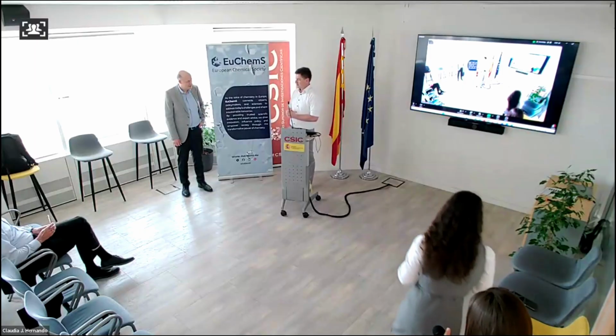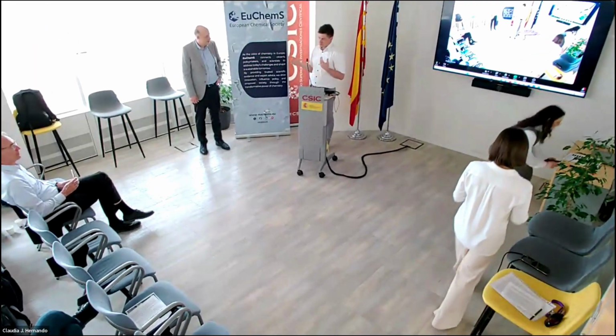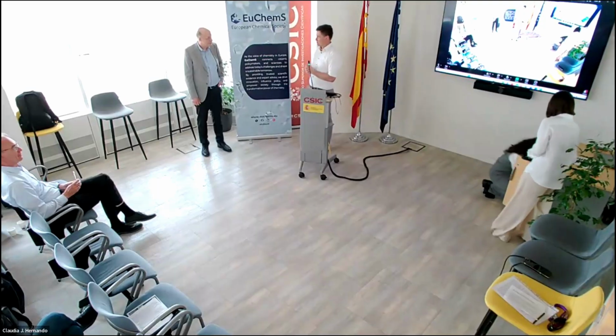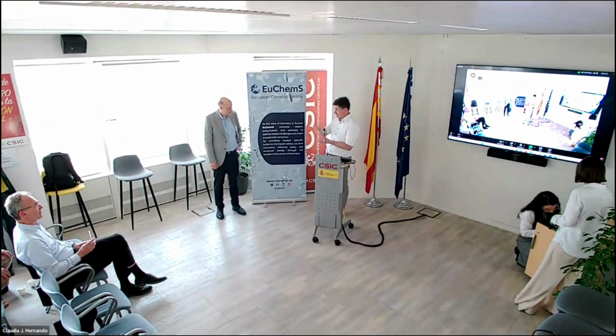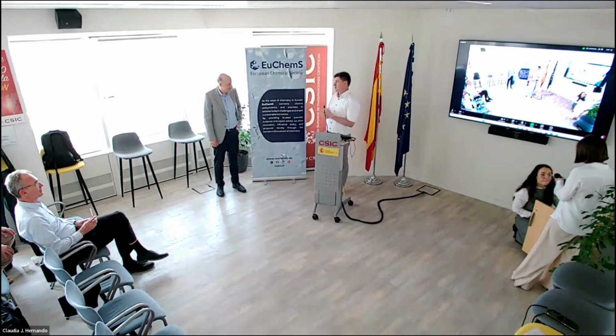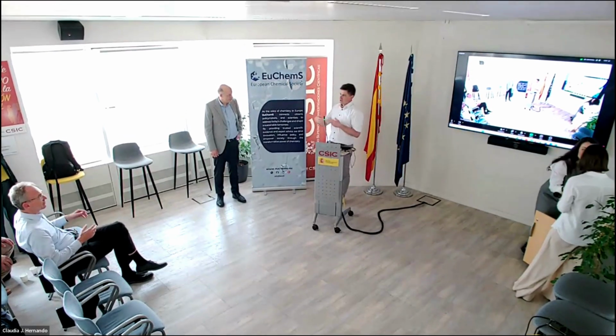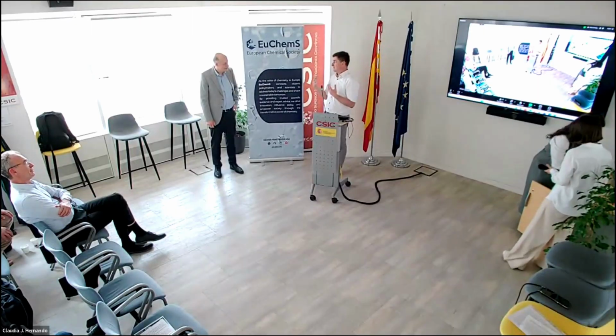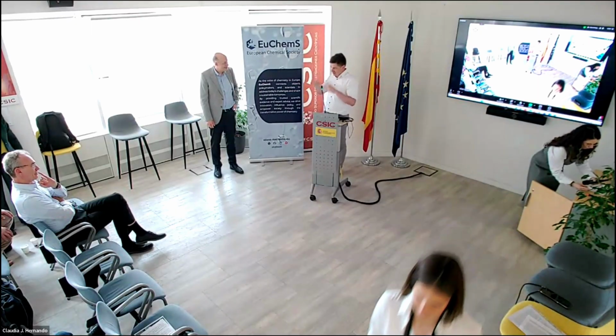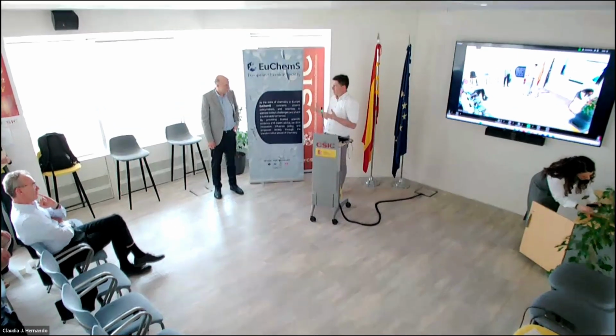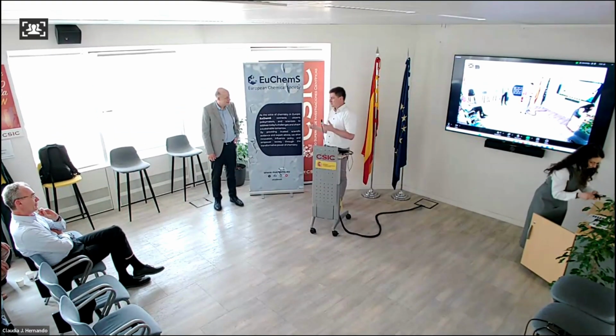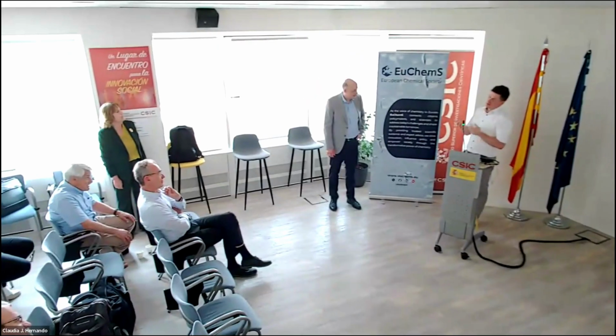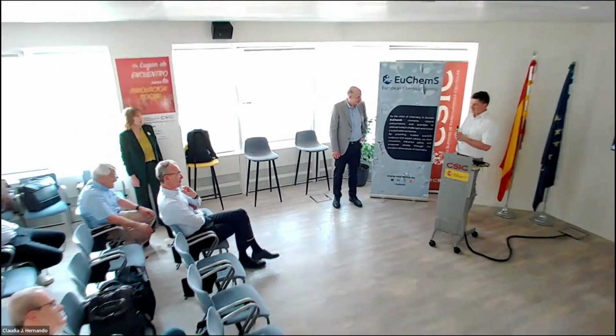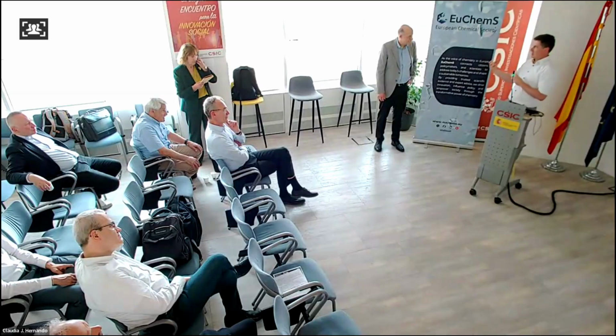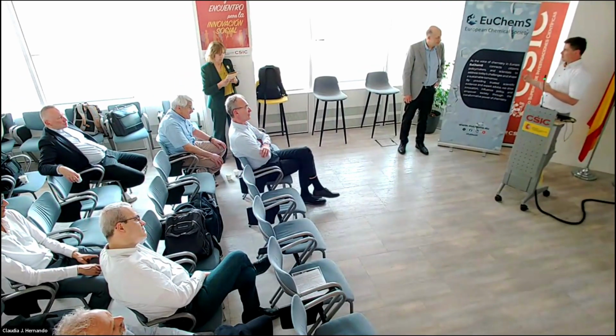So what you really need is to separate it. There is also work, for instance, in Japan, where they melt everything and then get the rare earth out from the liquid, which you can do, but you have the melting step. You can demagnetize it in the first place, where you need heat. But like I said, if you really smash it down, the magnets will get destroyed and it will be hard to collect them. So usually what happens is that these permanent magnets go into the iron, are recycled with iron, are formed as slag, and then they are lost.